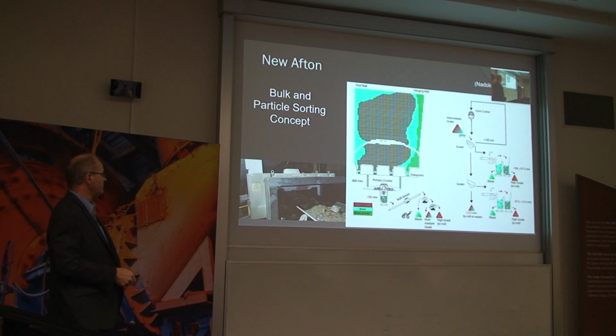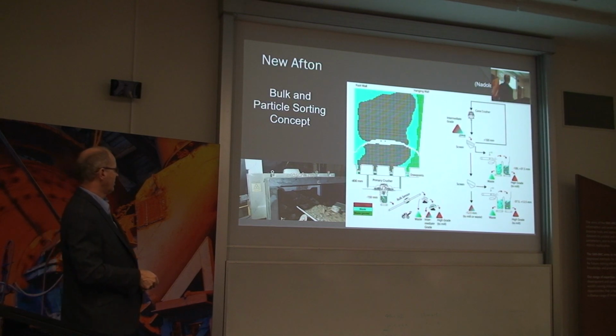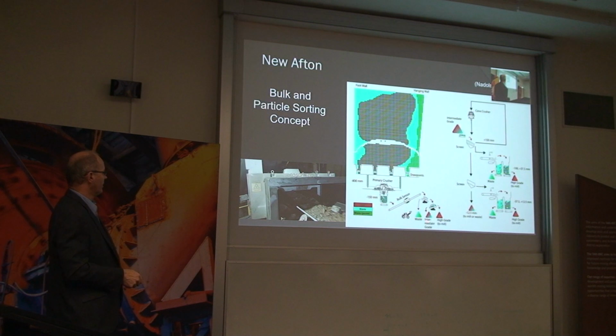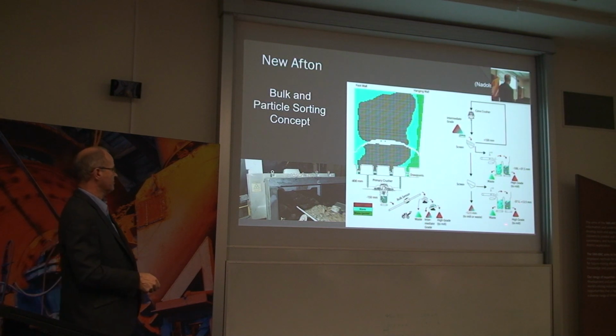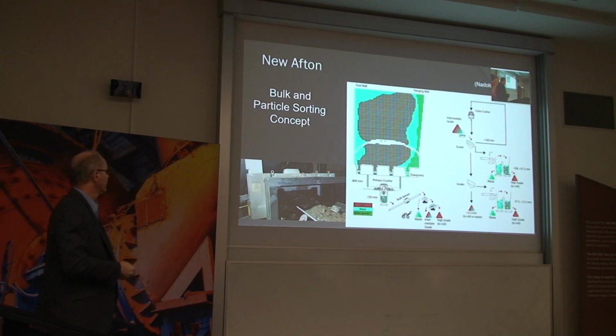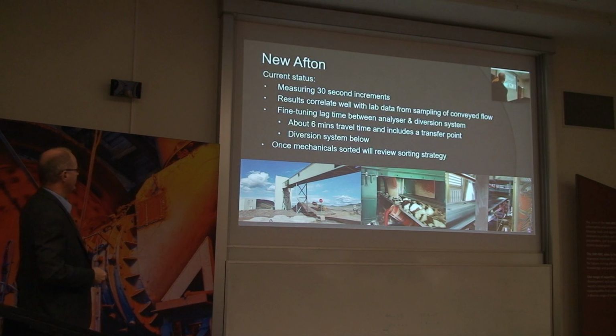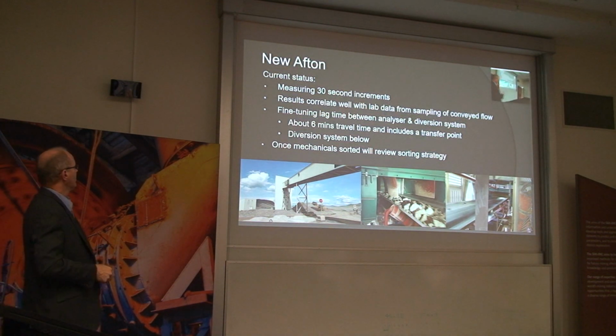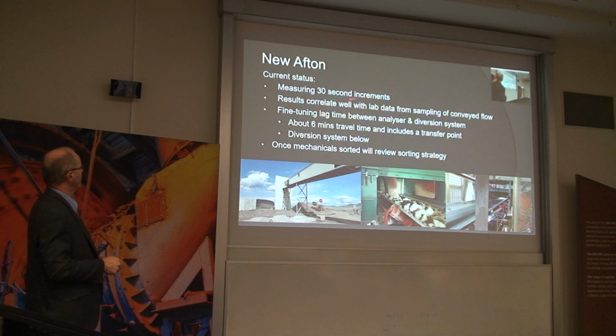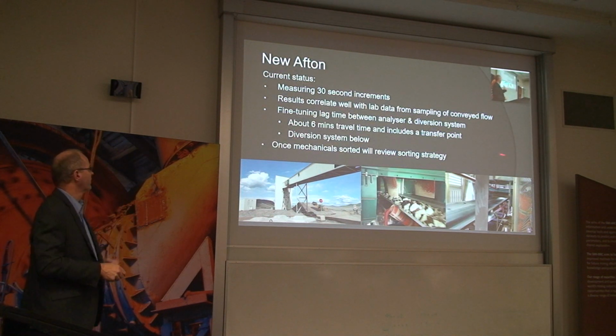because they cannot recover the copper from that material. The plan was to divert into 3 destinations: waste, low grade, high grade, and for the low grade or intermediate grade, they were looking at a 2-stage particle sorting process. That hasn't happened. They're still trying to work out if they can justify it. So this is how it's going. They're measuring every 30 seconds. The results are correlating well with sampling they're doing off the conveyor.